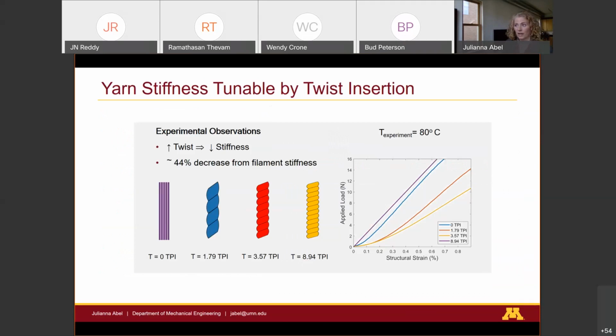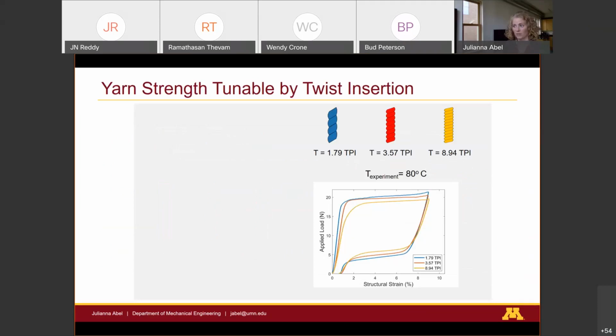So, some preliminary results. We've noticed that we see these strong trends that depend on twist. If we increase our yarn twist, we decrease the stiffness of the yarn. And the same thing with strength. As we increase the twist on the yarn, we're getting less and less strength. However, there is an optimal point.